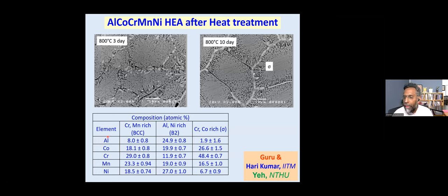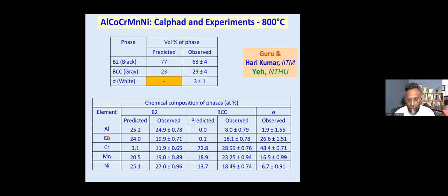And that tells you that, yes, it's important to find out whether any second phase can precipitate out of the single phases or not by doing various thermal exposures to various temperatures to find out whether the alloy is stable or not. All this can be done, but there are a lot of challenges in thermodynamic predictions of these multi-component systems because there are always certain assumptions which can make sure that your actual predictions may not come very close to the observed conditions. So that's where there is a lot of need for doing a thorough thermodynamic analysis to find out these phase diagrams, multi-component phase diagrams.